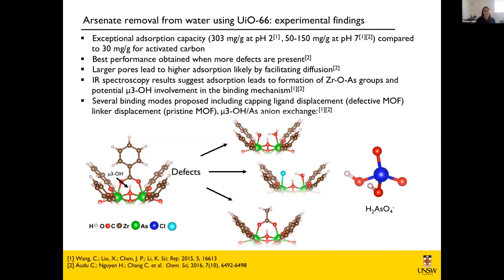And what they see is that essentially some zirconium-oxygen-arsenic bonding is being formed, which would most likely be formed if one of these linkers is kicked out of the structure, and then the arsenic can come in and use two of its oxygens to coordinate the zirconium atoms. The other thing that's observed is that this hydroxyl here, which is typically referred to as the mu3-OH, is also being affected, and so it might participate in the binding mechanism as well.